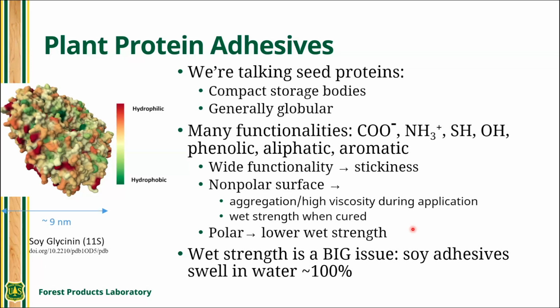These proteins have a lot of hydrophilic residues, and so you get a lot of water, and the swelling that we've been measuring is on the order of 100%. So double their thickness when they get swollen with water. Not great for wet strength.